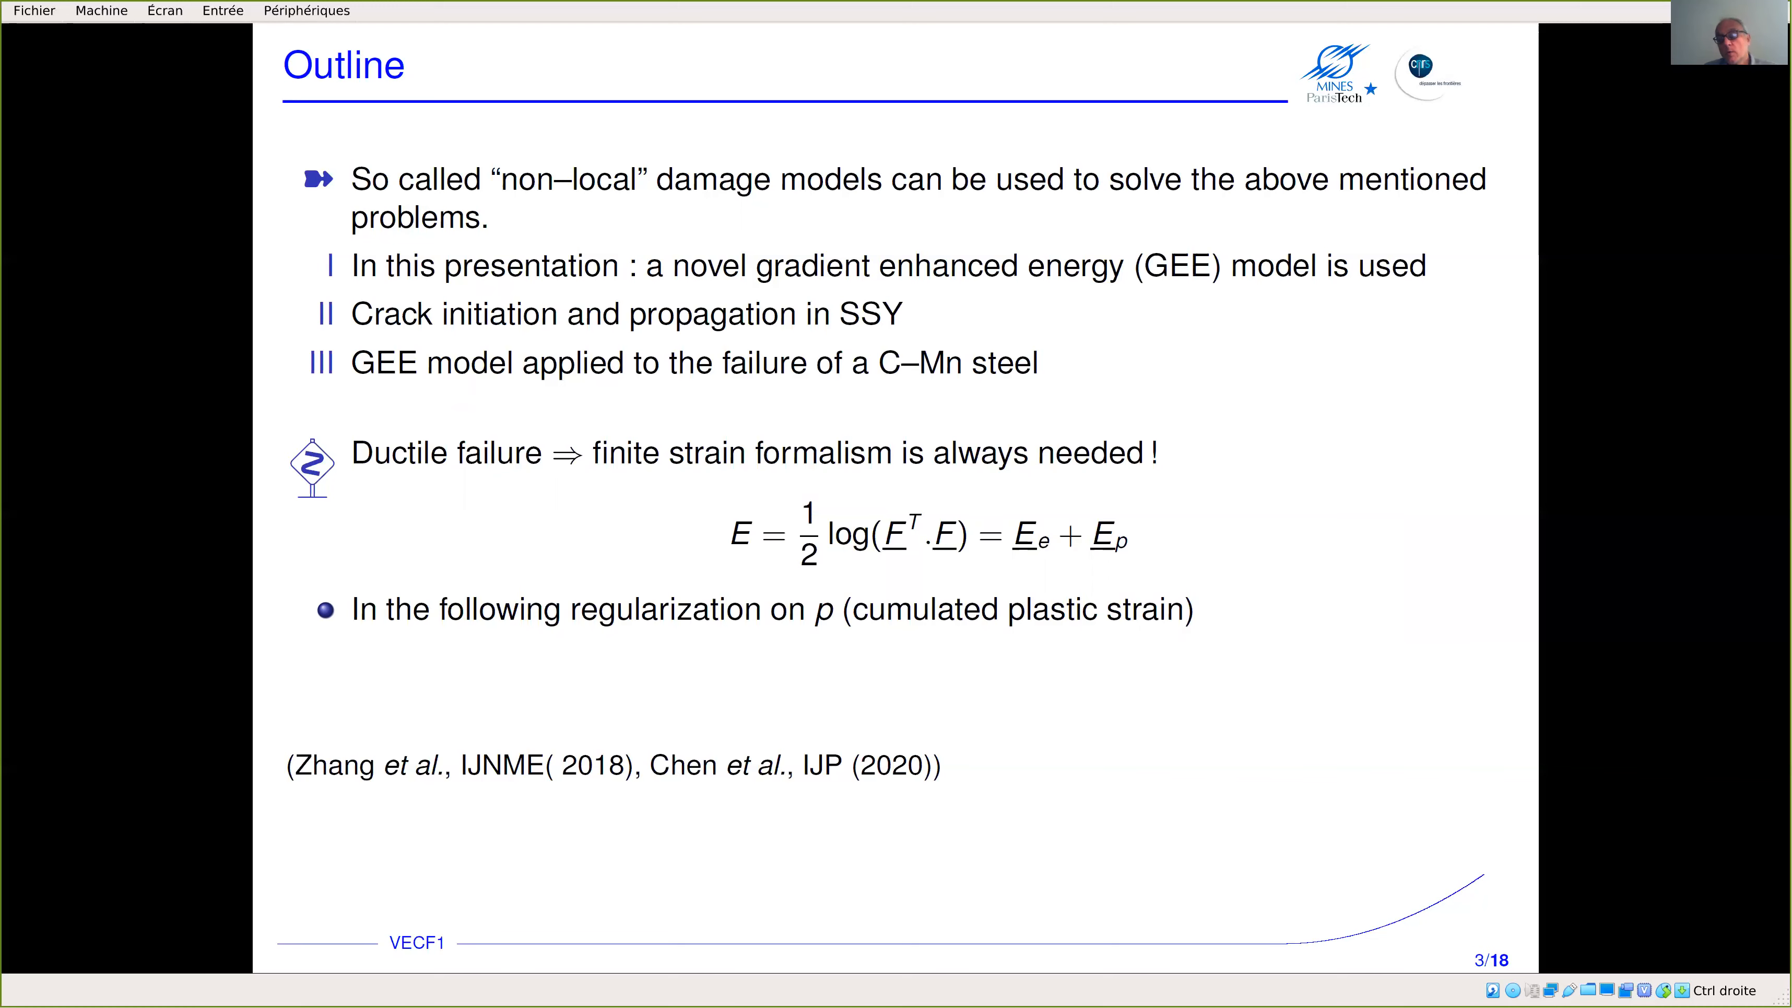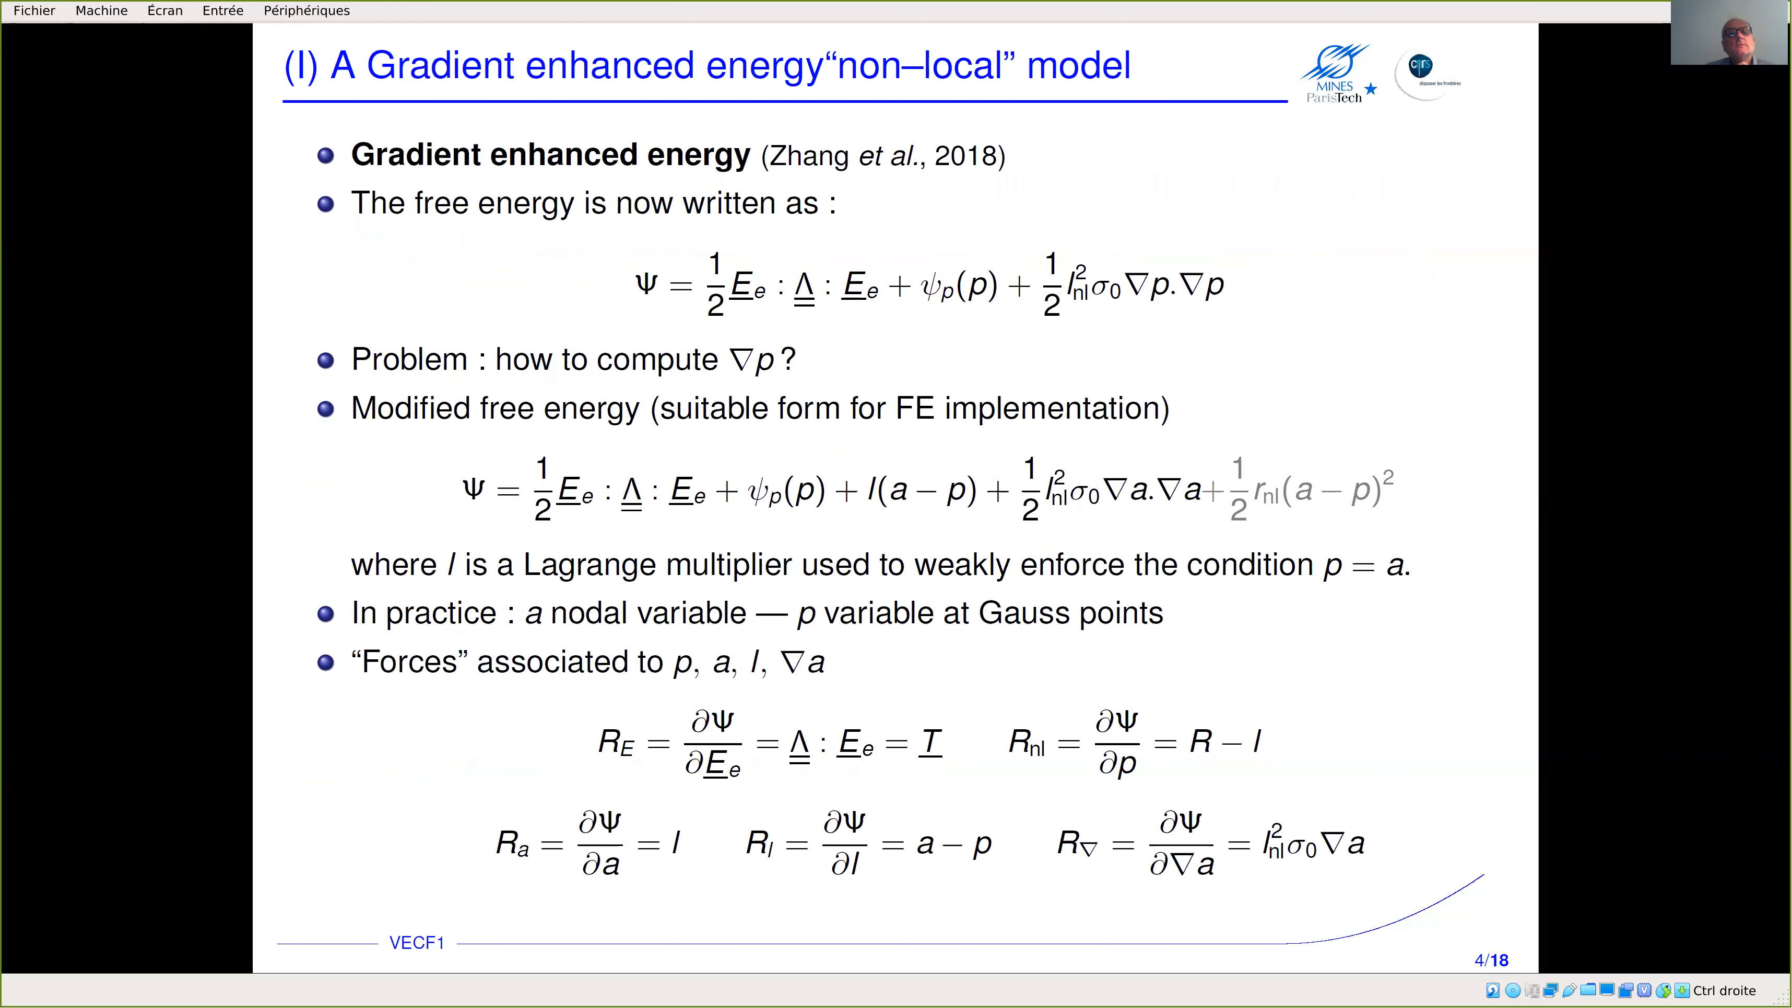Ductile failure is always accompanied with very large strain, so it's very important to use finite strain formalism. The one we use here is based on the logarithmic strain measure where F is the deformation gradient. F can be split into an elastic part and a plastic part so that the model can be written as if it was a small strain behavior. Our variable which we use for regularization is the cumulative plastic strain.